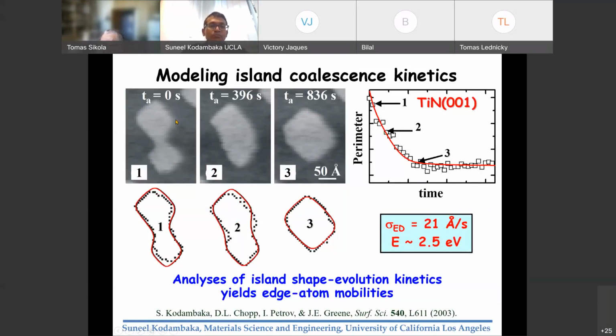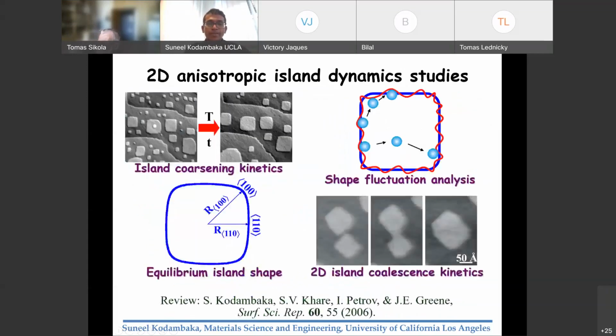And typically, atoms can diffuse along the step edges, or atoms can detach and reattach at other step edges. Depending on which mechanism contributes, you have a slightly different rate of change in the island perimeter as a function of time. By modeling this, we can account for this phenomenon, and from the time-dependent change in the shape of the island, we can extract the activation energy associated with this shape transformation process. Okay, so that summarizes my STM talk on the types of phenomena that one can study using scanning tunneling microscopy observations of island shapes and island sizes as a function of time.